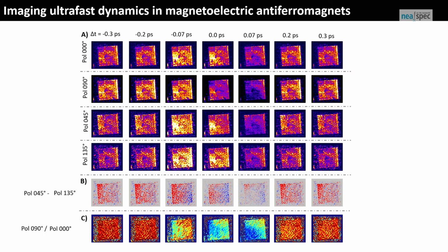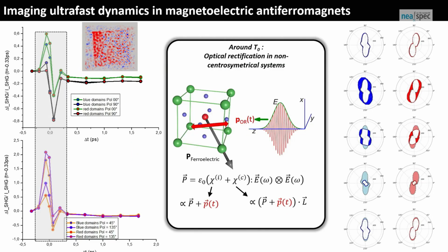And then once you have this antiferromagnetic pattern, you can select blue and red domains and look at their intrinsic dynamics. The idea we had here is basically, since it's a magnetoelectric, if we want to shuffle around the antiferromagnetism, we have to use ferroelectric polarization. And since it's a non-centrosymmetric material, if you shine an intense light on it, you generate a small dynamical polarization inside the material, which could be our ultrafast handle.